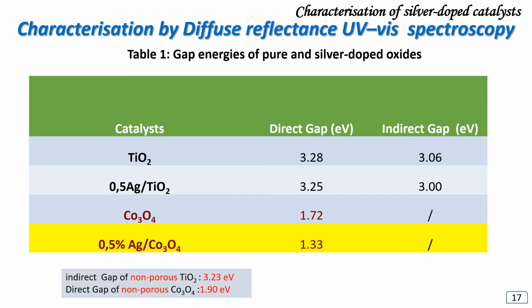oxide are lower than those reported in the literature for the corresponding non-porous oxides. It is important to note that the silver doping of these oxides resulted in the decrease of their gap energies. This decrease is explained by the fact that the silver nanoparticles introduced localized energy levels in the gap band of the pure oxides.